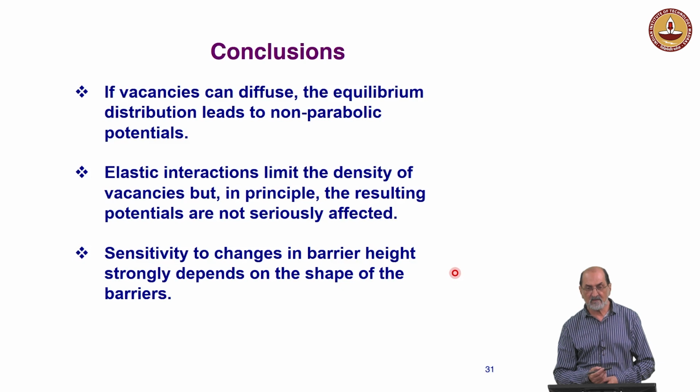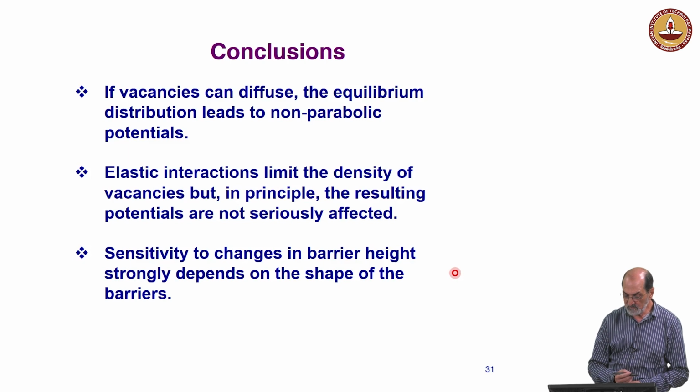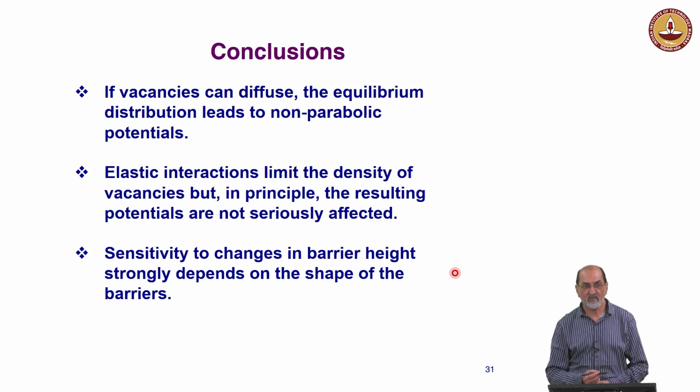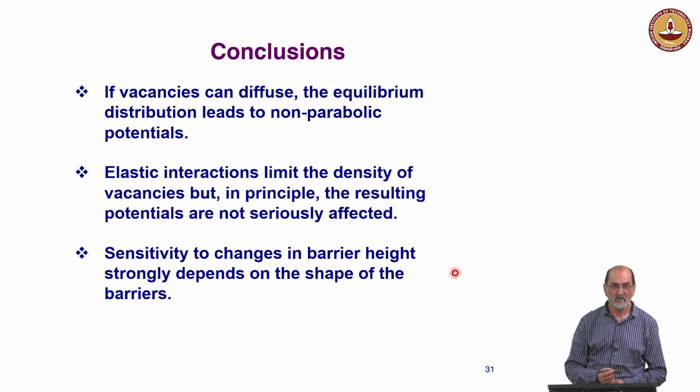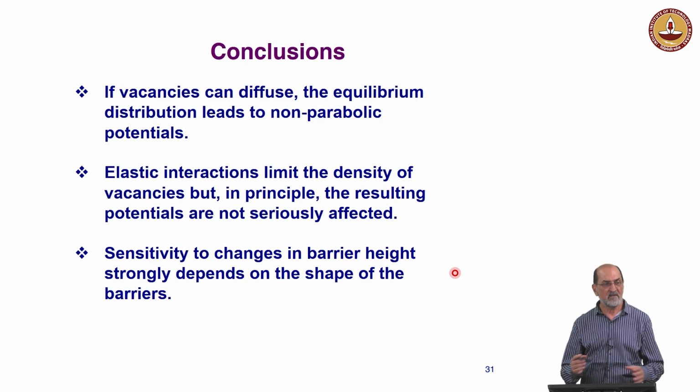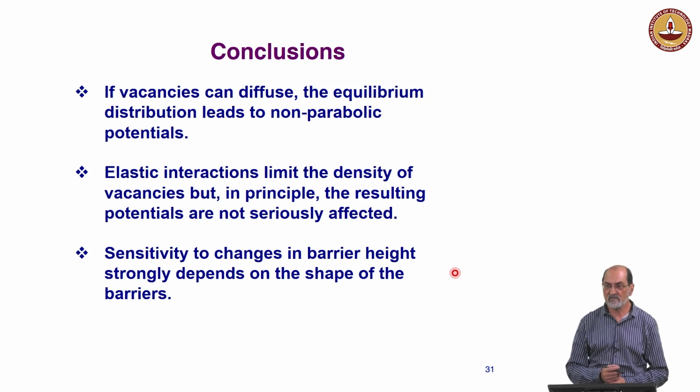I think that this could be one of the reasons, if not the most important one, why people are finding so different results, and why results depend so much on the preparation, because in preparing the samples, you have different density of doping, they were prepared in different ways, they came from low temperatures, some anneal the samples, others do not anneal them. And the results are very sensitive to all those details. Small changes in the dopant concentration can lead to completely different behavior.